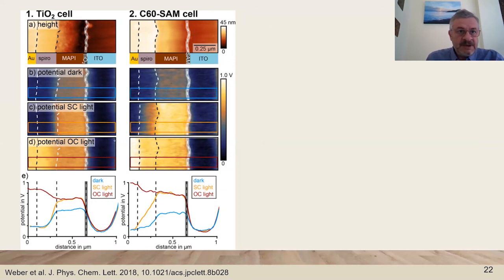This is the same experiment on a perovskite, on two different perovskite solar cells. The cell has been cut, and we see the different internal structure with the contacts and the active zone. And then we can track the potential by scanning the probe across the length and observe the internal distribution of electrical potential in different conditions of bias, light, etc. And we get a lot of insight about how the device is working inside.